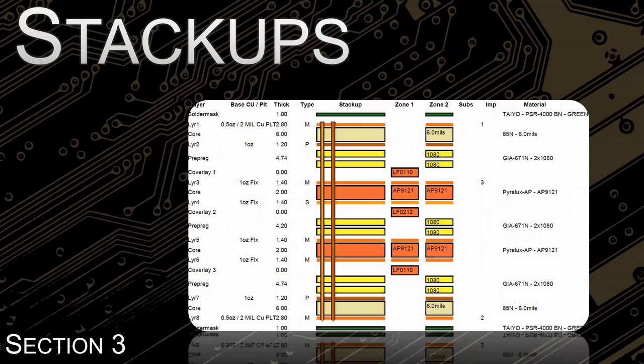Yeah, exactly. So one of the most common misconceptions we hear is, well, the thicker the board, the more expensive my board's going to be, right? Well, especially with rigid flex, that's not always true. It's actually the opposite. Once we fall under certain thicknesses, we not only have to change the machinery we use, but several automated processes now either need to be adjusted to accommodate those thinner dielectrics or have to be replaced altogether, right? So for instance, with flex material, standard mechanical drill is no longer possible. We have to use a laser drill just because the material's so thin. If we use our standard drill bits here, it's going to grab that like a piece of paper and just crumple it all up.